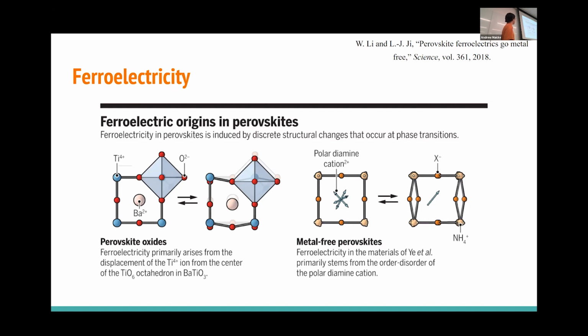For example, here we have a perovskite ferroelectric. Using an electric field or strain, you can move the location of the titanium 4+ ion relative to the crystal structure. When you do that, you're essentially redistributing the charge and creating an electric polarization. Ferroelectrics are useful because you can use them to store information, like with magnetic memory.